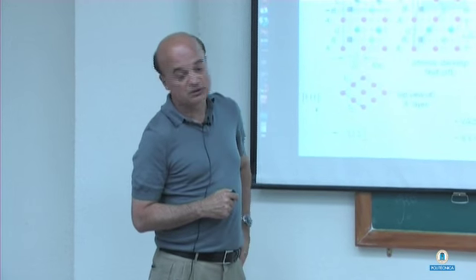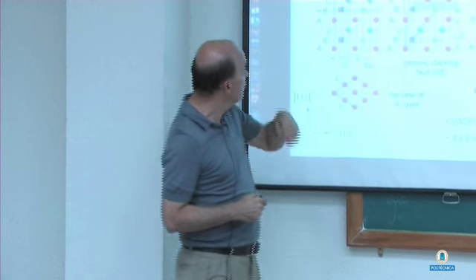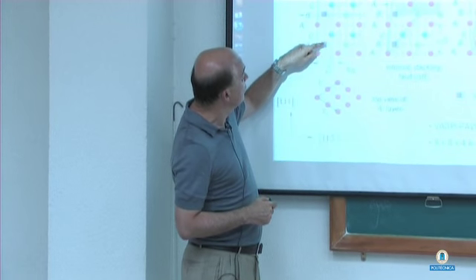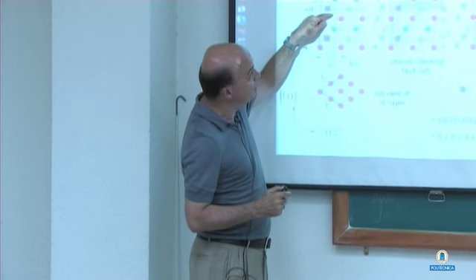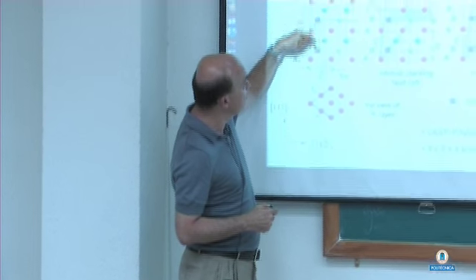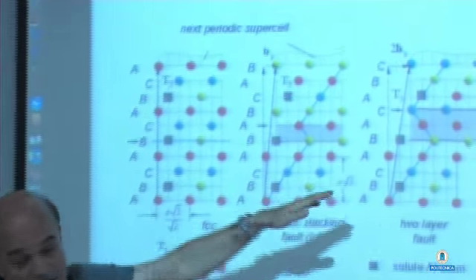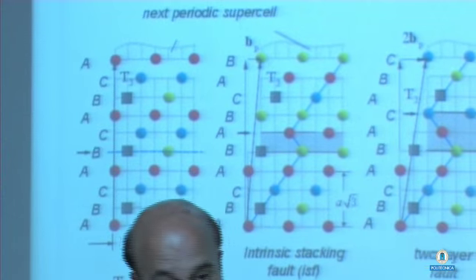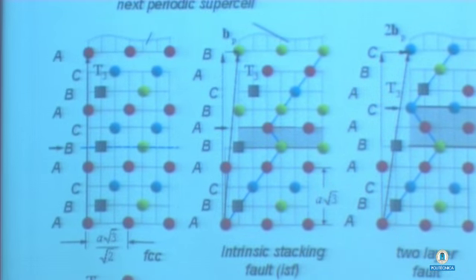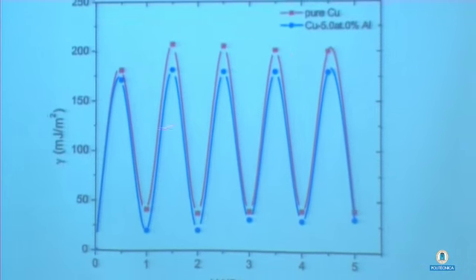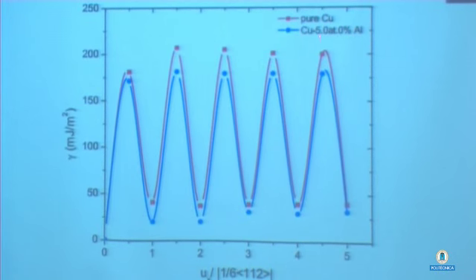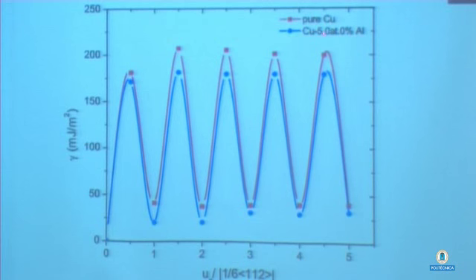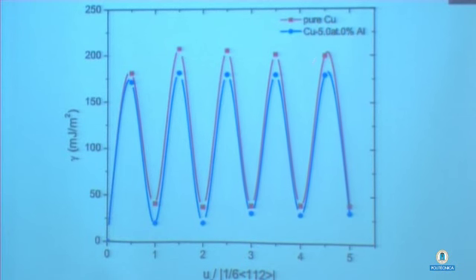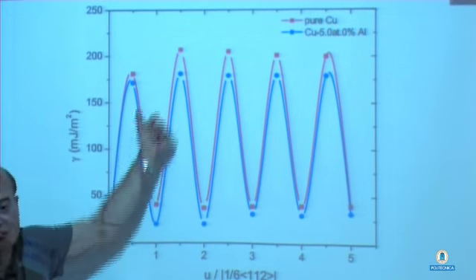Copper-aluminum alloy results, and aluminum is put in at 5.0%. These are aluminum atoms here. And then again, the same idea. You create a twin and you look at the gamma curves. They are different. This is pure copper, and that's copper with 5% aluminum. You could see the barriers have come down.